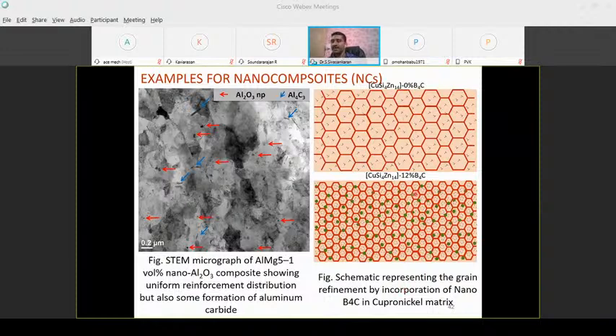But here, during heat treatment or at some elevated temperature, the matrix grain will never propagate, maybe a little. Why? The presence of nanoparticles occupies the grain boundary. Therefore, it will try to pin down or inhibit the growth of the grains. That's the benefit of nanomaterials.